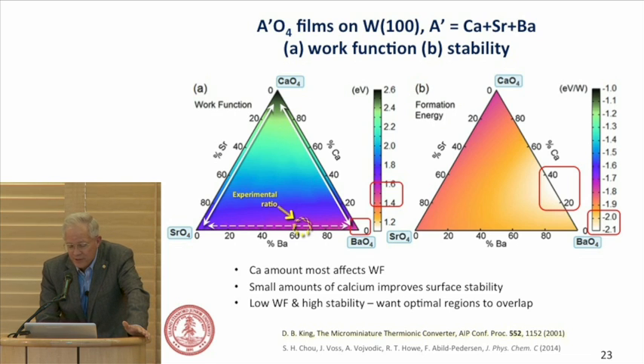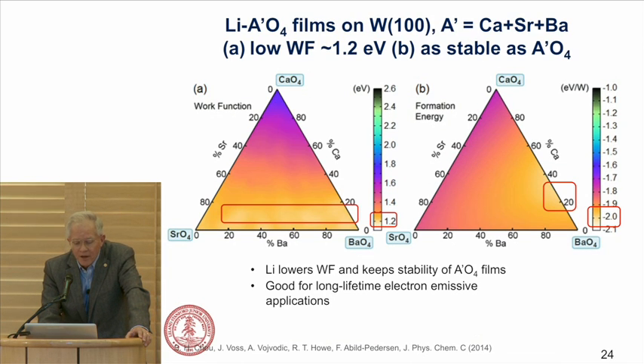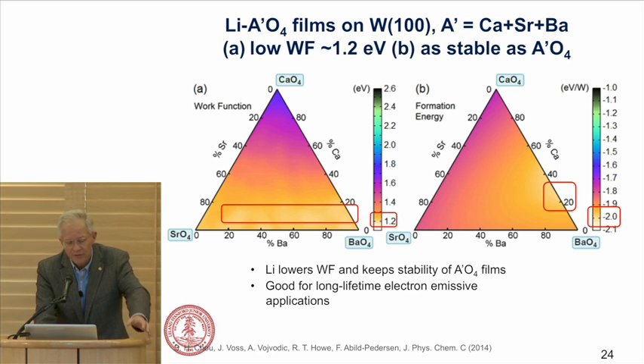However, it's making the formation energy lower, so it's a kind of counter effect. And so you may be able to see adding a pinch of calcium to get that surface stability while maintaining the low work function. Now, there is an experimental ratio here from a paper about 13 years ago, and so we would be benchmarking in the very limited experimental data.